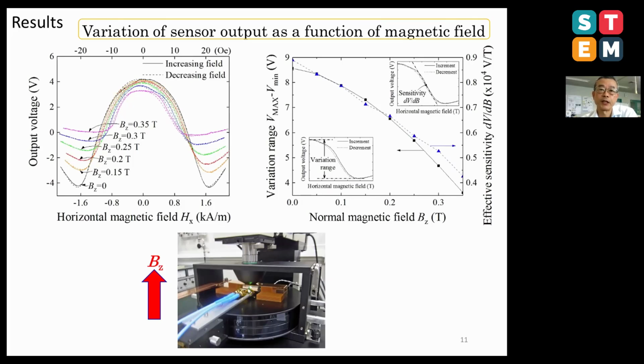This sheet shows the variation of sensor output as a function of the applied normal field. The left figure shows variations of sensor output as a function of sensing magnetic field. The normal magnetic field was a parameter, and the normal field varied from 0 to 0.35 Tesla. The horizontal magnetic field, which corresponds to the sensing field Hx, was controlled by the horizontal coil. The profile of this sensor output is a vertical inversion of the element impedance previously shown. The reason is that the signal level coming out from the sensor element is inversely proportional to its impedance.